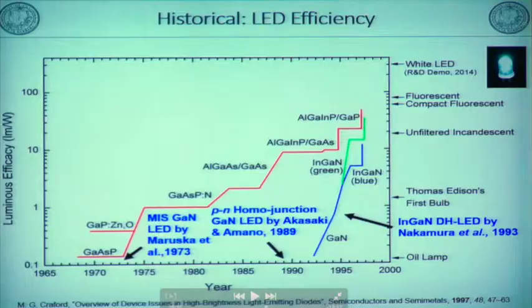This shows the luminous efficiency of the red, blue, and green LEDs. Basically, the red LED was invented in the 1960s by Professor Nick Holonyak of the University of Illinois, and the efficiency of red LEDs gradually increased. The InGaN based efficient blue LED was invented in '93. Then the efficiency of the indium gallium nitride double-heterostructure LEDs increased dramatically, and the white LED is the same.